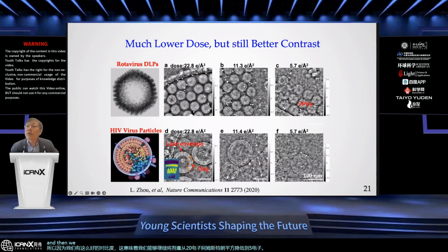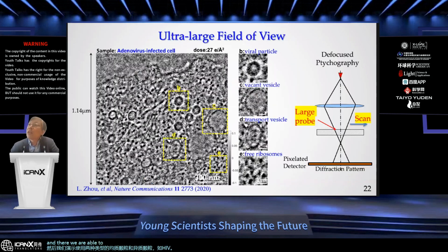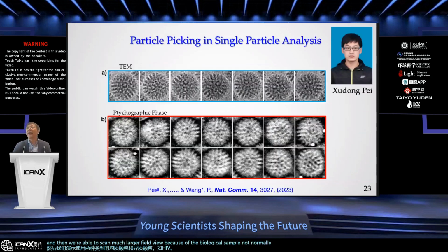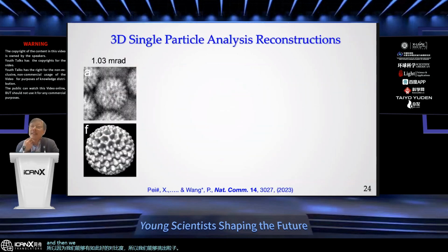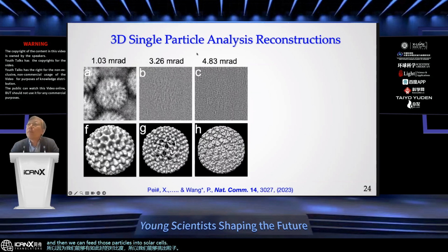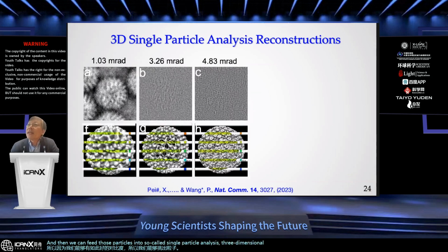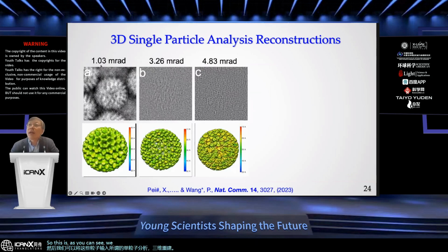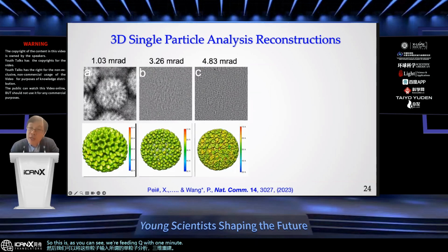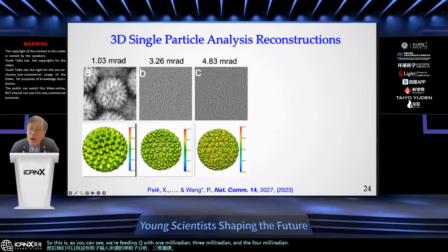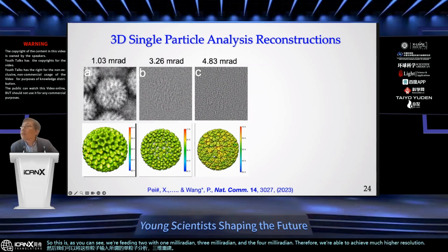And then we demonstrate using both homogeneous particles and also heterogeneous particles like HIV. We're able to scan a much larger field of view, because biological samples normally have a larger size. Because we have such good contrast, we're able to pick the particles out, and then we can feed those particles into so-called single particle analysis, three-dimensional reconstruction. So this is, as you can see, fitting with 1 milliradian, 3 milliradian, and 4 milliradian. Therefore, we're able to achieve much higher resolution when we increase the convergence angle.